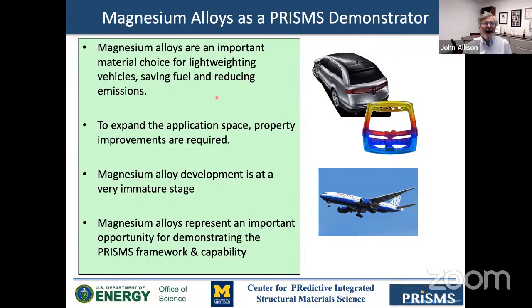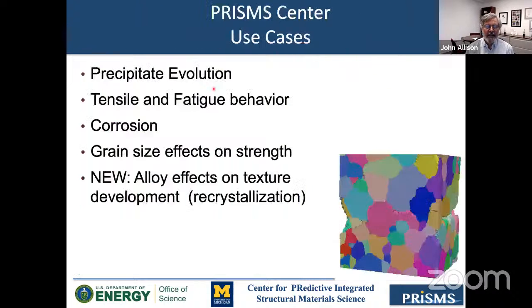To expand applications in those domains, property improvements are required. And magnesium alloys are a little bit immature. Typically, alloys are ternary alloys of magnesium and aluminum, and either manganese or zinc. Certainly there are other alloys, but these are the lion's share. When you compare that to an aluminum alloy or nickel alloy, it may be 10 elements. And so there's a lot of opportunity for improvement in magnesium alloy technology. And so we thought that that was a good framework, plus lightweighting fits the DOE needs.